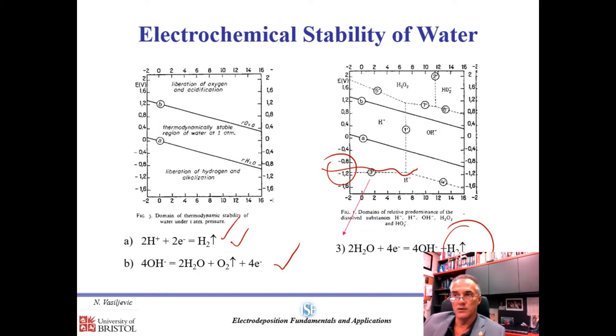And the water molecule, in terms of molarity, is 55 molar per liter. So once you enter this regime, most of your current will be related to the water reduction, really less to metal deposition. If you don't have to go there, I strongly suggest you think twice why you also want some high current density if you're going to be reducing water.